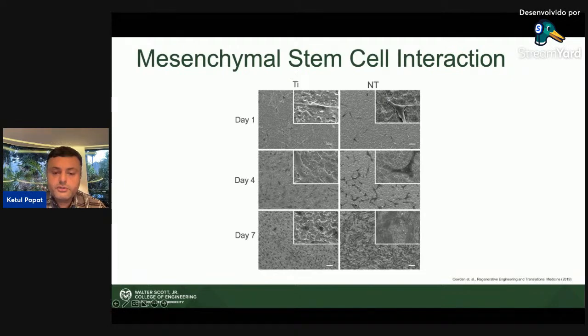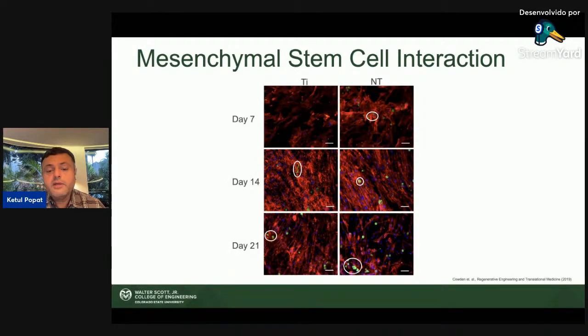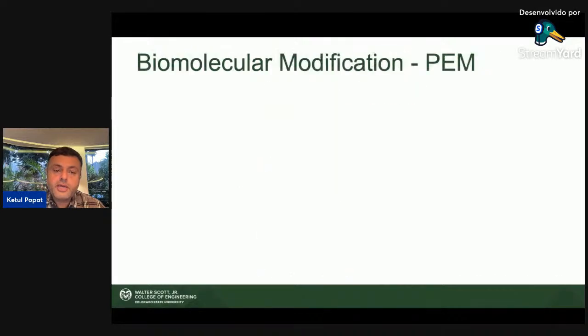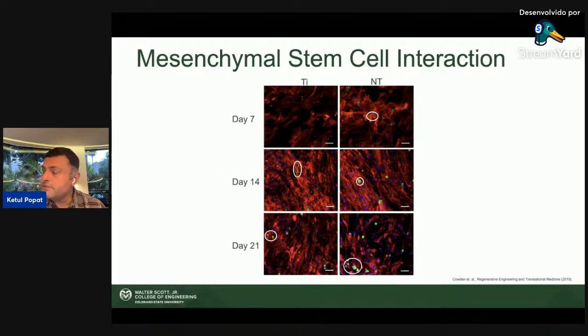This is an SEM image which shows how the cells are all interacting with each other. And what we find out is that when we start growing these cells for a long period of time, we see that these cells are producing proteins which are part of the bone, which is important. At this point, you can see that the number of cells is all the same. Everything is covered. But the cells on the nanotube surface have a lot more green dots. This green dot represents a specific protein called osteocalcin, and this osteocalcin protein is really critical for the health of the bone. So if osteocalcin is produced on the surface, that means the cells are happy, and eventually the cells will grow new bone, and in that way you have a good binding.